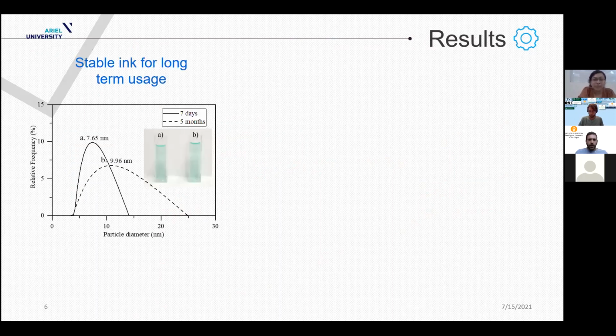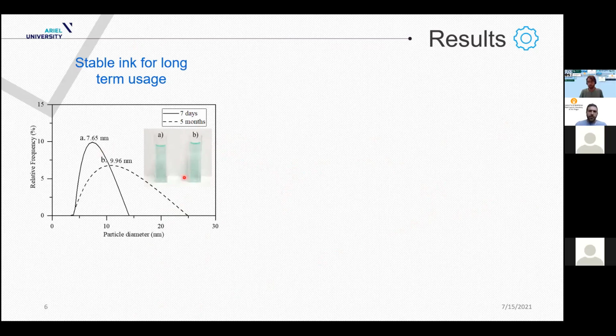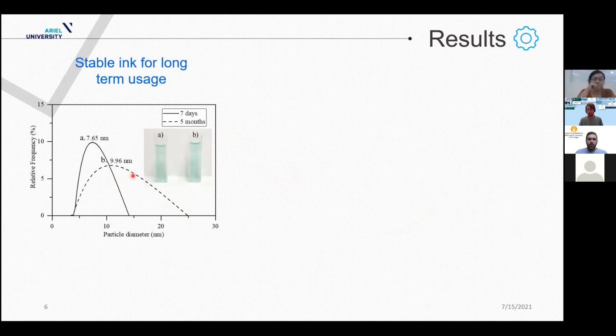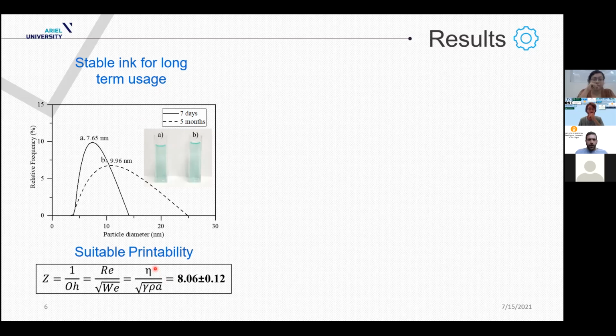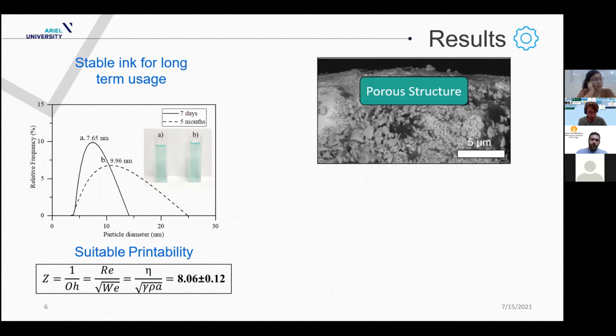So if we go over the results and characterization, the synthesized ink had relatively stable particle size over time, which means we can use it for long periods. The rheological properties of the ink are suitable for printing as synthesized, which means that the viscosity, density, and the surface tension of the liquid were suitable for this specific printer.